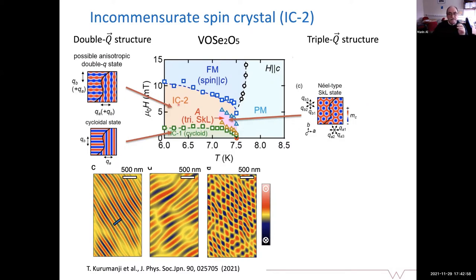Then you have another phase, which is called IC2. And this is the double Q phase, in which you have this modulation of the initial periodic phase with the second periodicity along its own structure, you see here, like this. And this has been called an incommensurate spin crystal. Why incommensurate? Because it doesn't fit with any crystallographic periodicity. So it has its own periodicity by itself, which is decoupled from the crystal. And it's very nice.